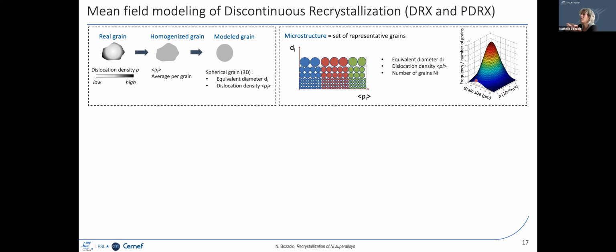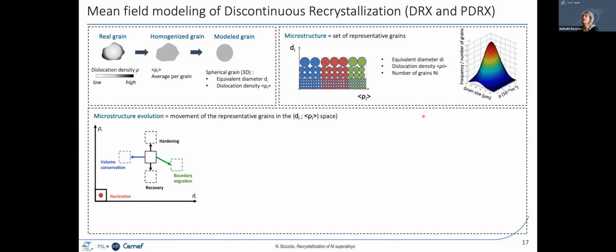And you have to describe the population of each of these grain types. Then you have to make them evolve. So evolution can be due to work hardening. There you do not change the size, you increase the dislocation density. Recovery has the opposite effect. If you have a boundary migration there, then the grain grows.